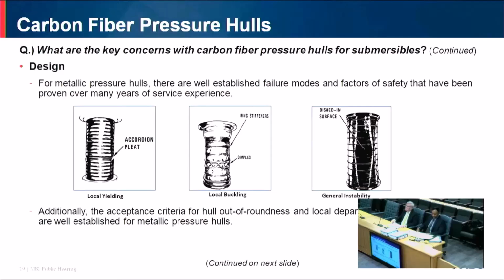So all of these failure modes are well established, they have many years of service experience, and the factors of safety are well proven through service experience on many different submersibles. Additionally, the rules also have a well-established acceptance criteria for hull out of roundness and local departure from design geometry. So when you have a pressure hull which is exposed to external pressure, it is very important to maintain out of roundness of the hull, okay? If the out of roundness of the hull goes beyond specifications, it can cause premature collapse of the hull. So out of roundness is absolutely critical when you have a pressure hull which is exposed to external pressure.